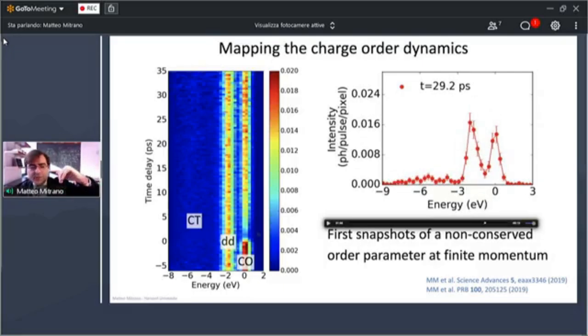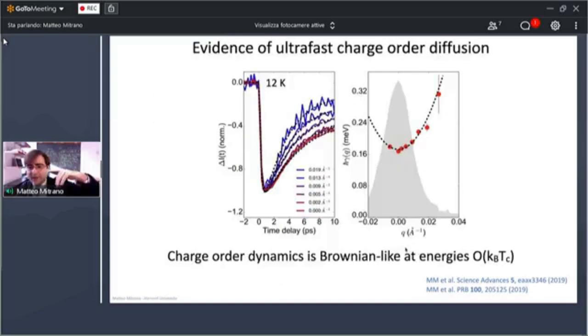Let me say one important thing. If we focus on these short-term dynamics and we start sampling them as a function of momentum, so we start scanning in momentum space, we can actually see that the time it takes for the order parameter to go back to equilibrium is not constant. It actually varies with momentum. And the fact that it varies with momentum tells us that the recovery is faster when you go out of the diffraction peak and into the tails of the diffraction. And if you extract the time constant from this exponential relaxation, and you plot the relaxation rate as 1/tau as a function of momentum, you can actually see that this relaxation rate goes quadratically with momentum, therefore telling you that the recovery dynamics is diffusive.